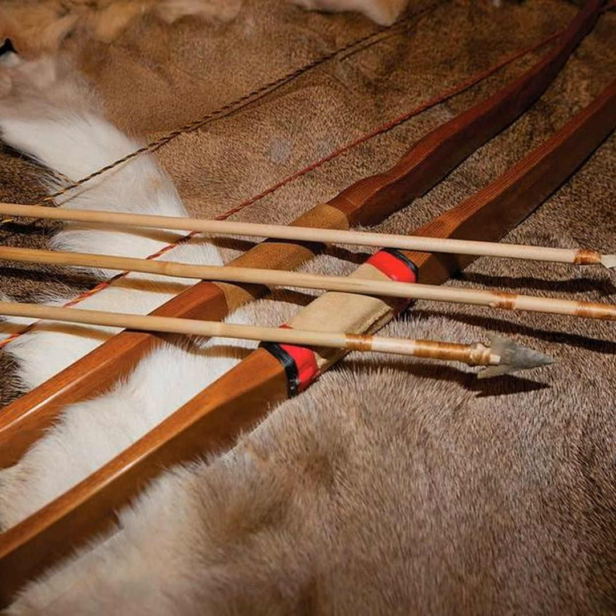Now, what do we say? Osage orange was what? We'll just say 18,700. Balsam is 8,800. So yeah, like a third, not quite. Sorry, little more than half its bending strength. The MOE of Osage orange is 1.7 million, rounding up a little bit. Balsam is 1.3 million. So, not quite as big a delta there, but it's still a pretty big delta.